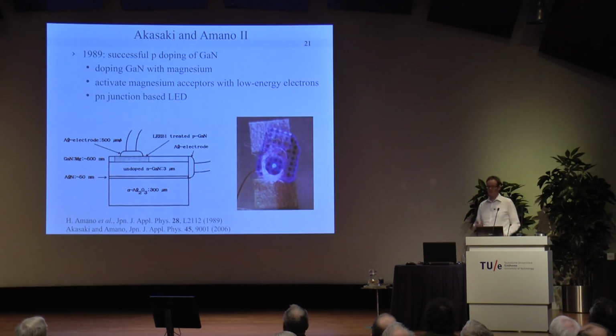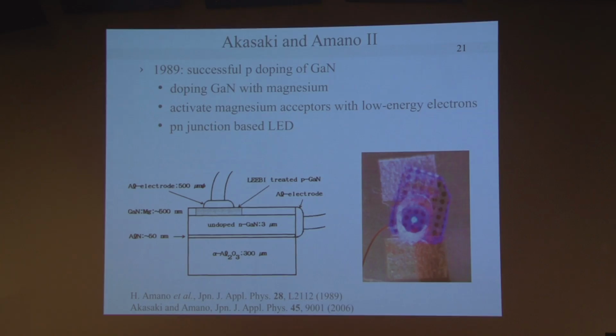They published more of these papers. Actually, so that was one problem solved, right? The crystal quality. Now they switched to the P-type doping. In 1989, they published a paper where they successfully demonstrated this p-type doping, and they doped it with magnesium. Now, this was tried before, so that is not, I guess, the critical component of that paper. But what they found is that they needed to activate the magnesium by using low energy electron beam radiation. And then they made the first real PN junction-based LED.